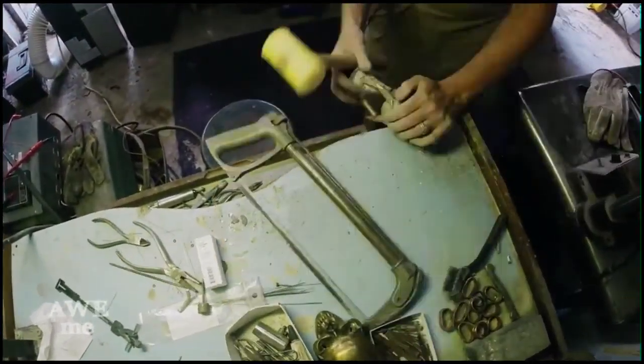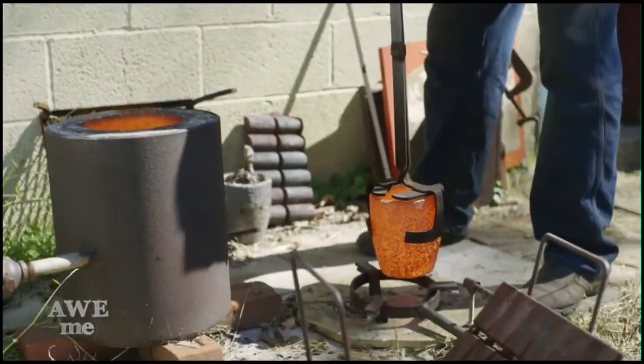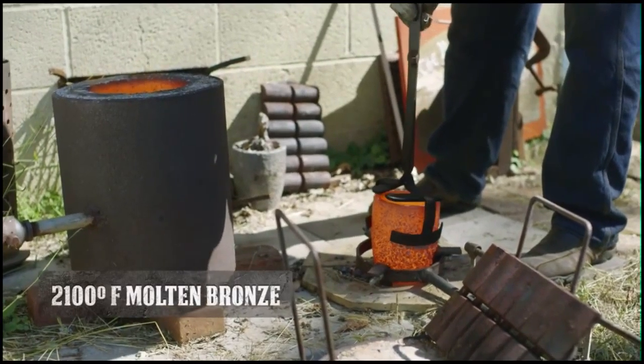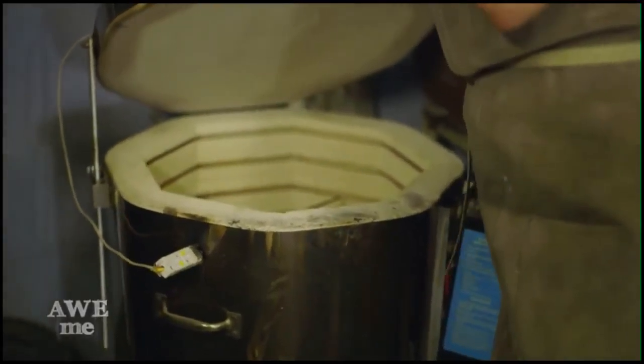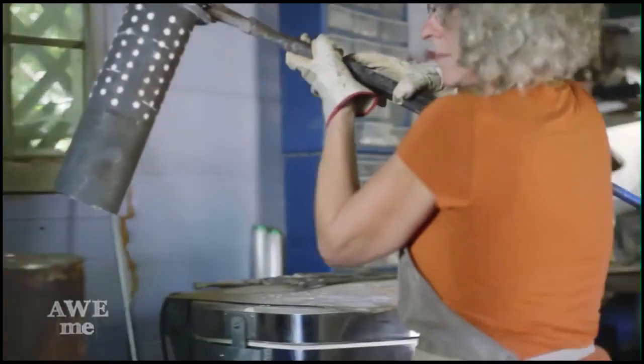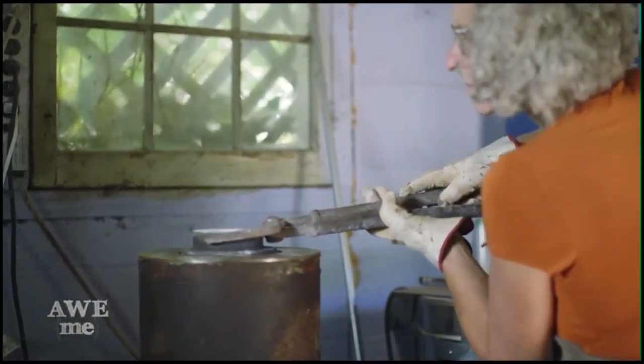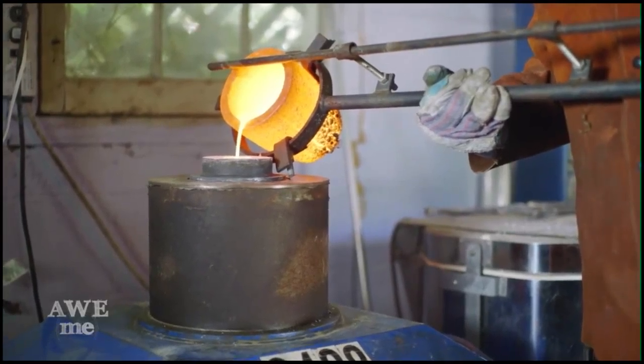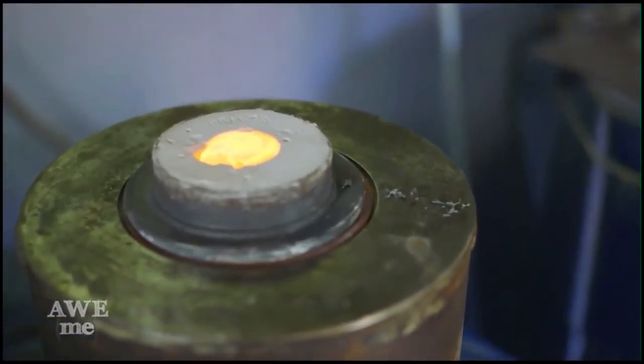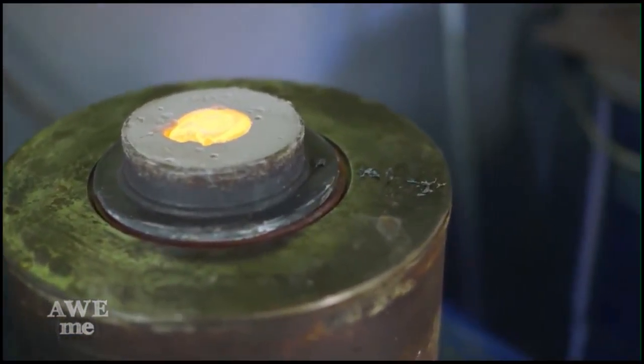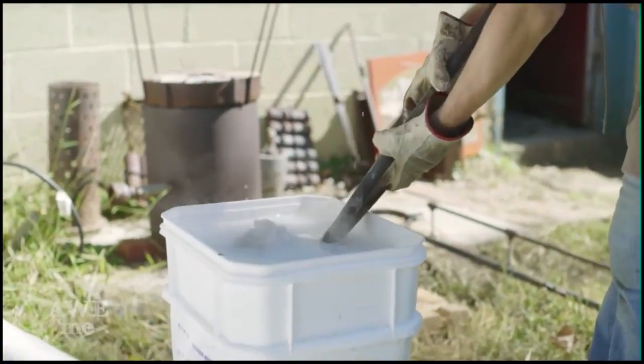Now that we have all of our hilt parts cast, in a gas foundry, we bring the bronze up to 2100 degrees. In the electric kiln, we have the flasks between 950 and 1000. We pull out the flask, set it in the vacuum unit, and pour the bronze. Now that the bronze temperature has fallen below 900 degrees, we quench the flask in water and it shows that the casting is perfect.